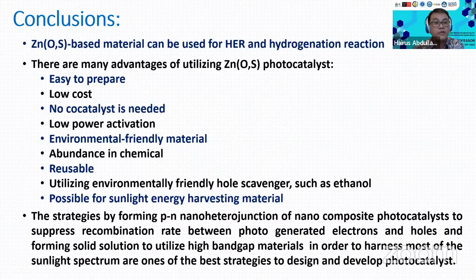Okay, finally I would like to conclude that Zn(O,S)-based material is very good for the hydrogen evolution reaction and also for chemical reactions such as hydrogenation. There are some advantages that I should mention for Zn(O,S) photocatalysis: easy to prepare, low cost, no co-catalyst needed, such as Pt or Au, and low power activation. We just use only a 16 watt UV light, so very low power, and environmentally friendly materials, abundant, reusable, and we also use a very friendly hole scavenger such as ethanol.